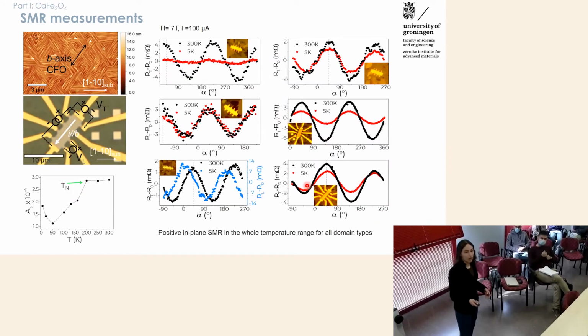And what we also did, because our first question was whether this can arise from imperfections and defects that we have at the interface between all these crystallographic domains, was build very small Hall bars, specifically addressing each individual crystallographic domain. And what we see here is that the SMR is always positive. So it's even different from what we would expect here. The sign is always positive, which means that the ferromagnetic contribution in these smaller Hall bars is larger, but the trend is always the same as the larger bars.